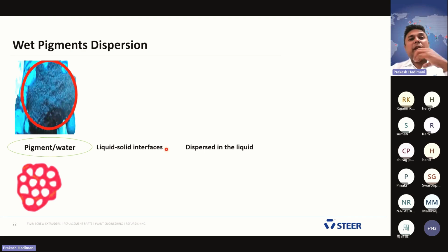The moment you remove water from the media, the pigment will tend to re-agglomerate. But if you keep it in the liquid mode with the polymer when we disperse, and later use a dewatering mechanism to remove the water from the system, that is what we call dispersion in the liquid media. That is the difference between dry pigments and wet pigments.